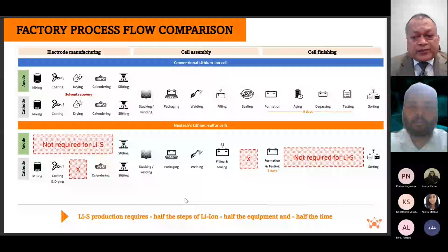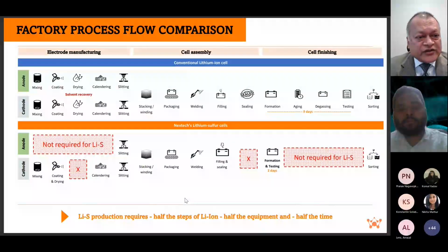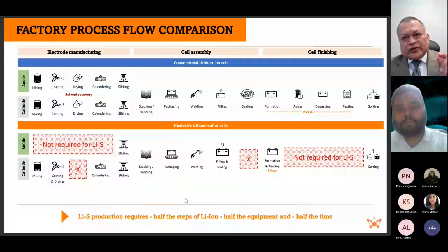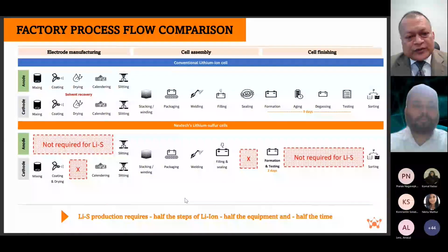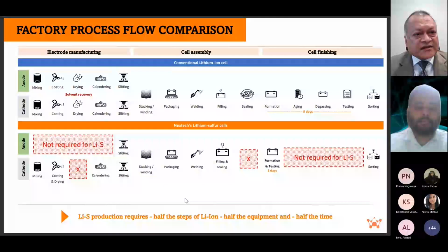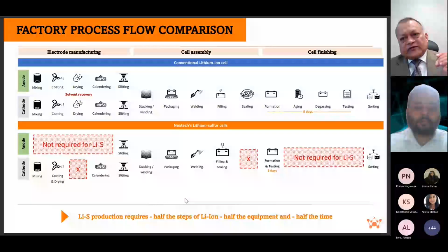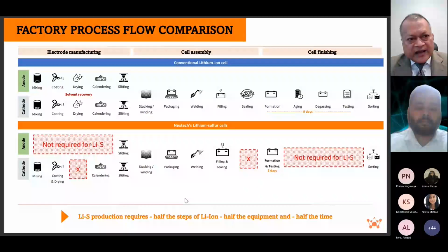And in our case, the entire process takes 2 days. That means the in-process inventory is going to be significantly less. That means the plant square footage you have is going to be substantially less. So when you combine no pasting requirements for anodes and formation cycle going down to 2 days, you reduce the plant size by almost 40%. So that means your break-even point for lithium sulfur goes down significantly, both from lower bill of materials, lower capex, smaller plant. You're probably looking at 800 megawatt hours to 1 gigawatt hour commercial volume to break even. Next slide, please.